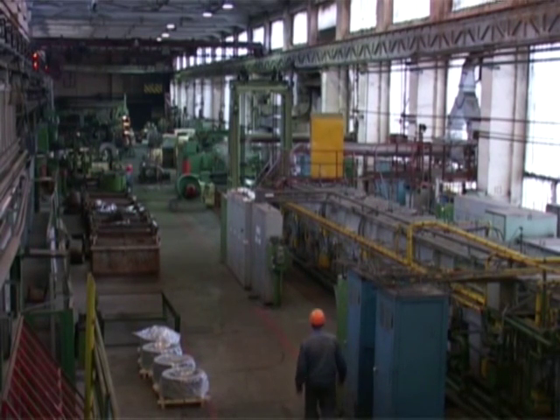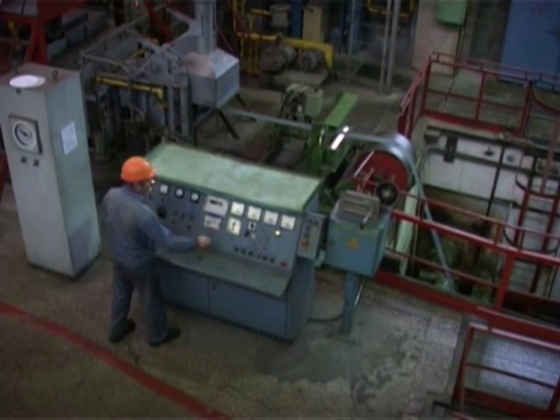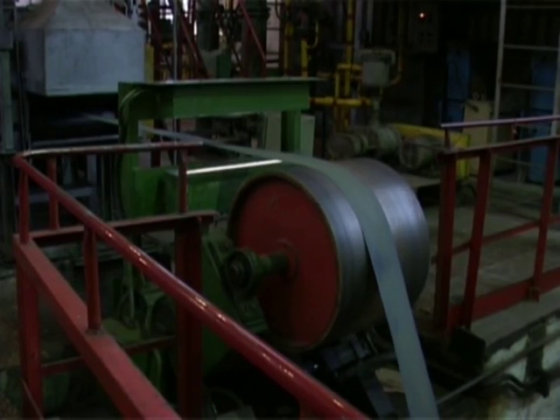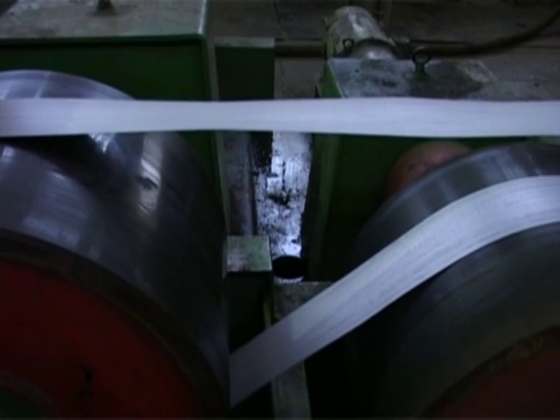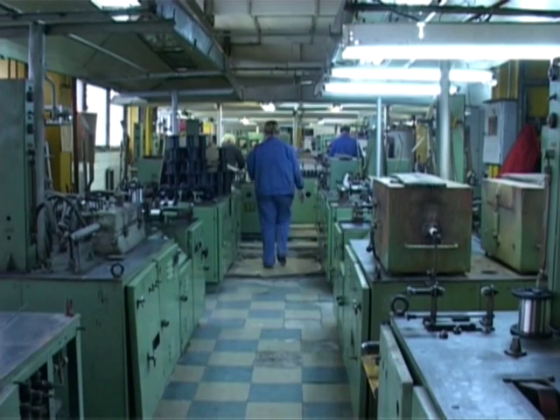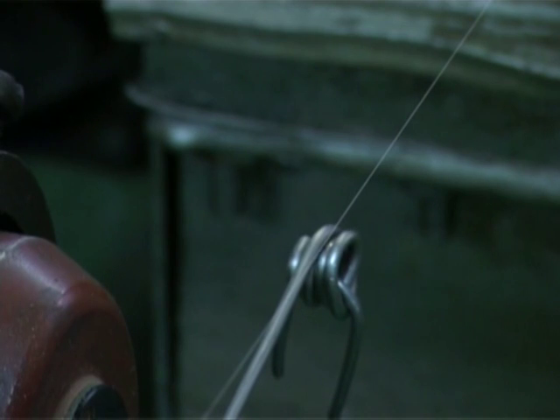The specialized equipment available at the plant enabled Electrostal specialists to master production of about 200 grades of precision alloys and 15,000 items of the shape and grade range of products: hot rolled sheet with a thickness from 3 to 25 mm, cold rolled strip with a thickness from 10 micron to 2.5 mm, and cold drawn wire with a diameter from 20 micron to 7.5 mm.